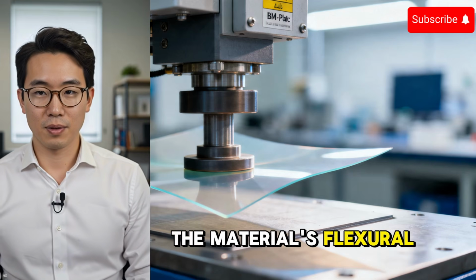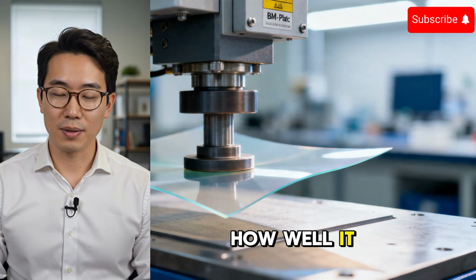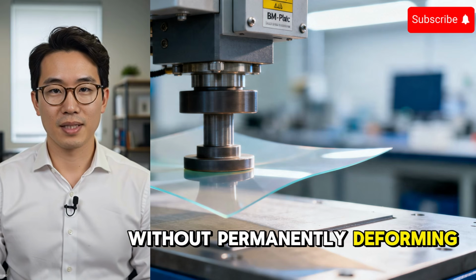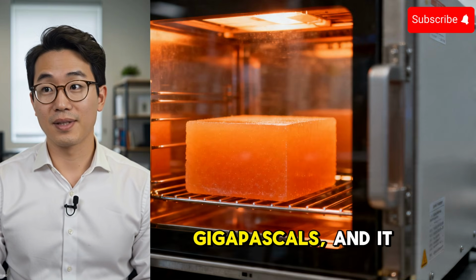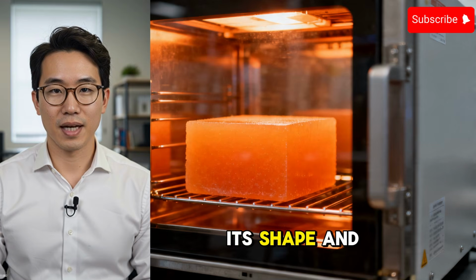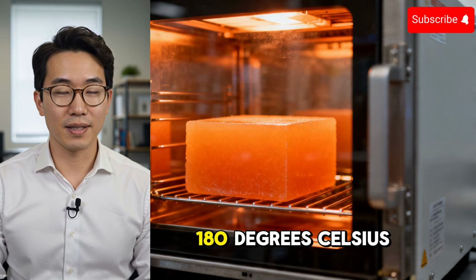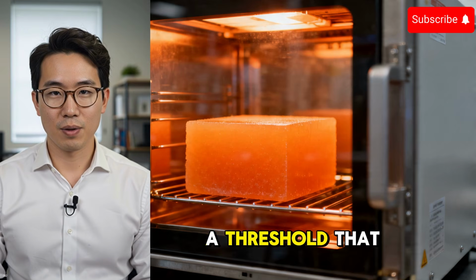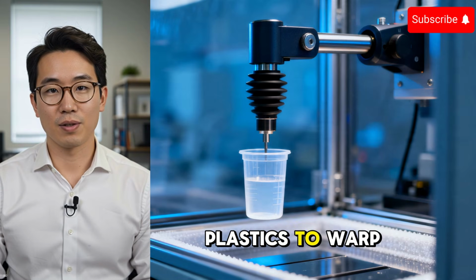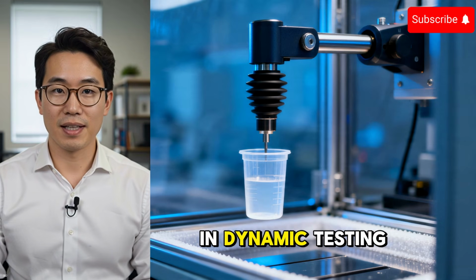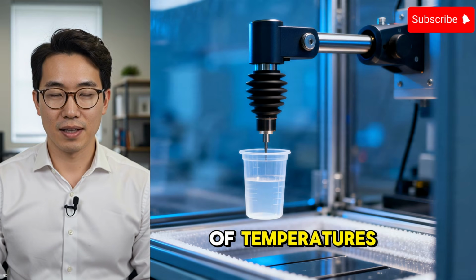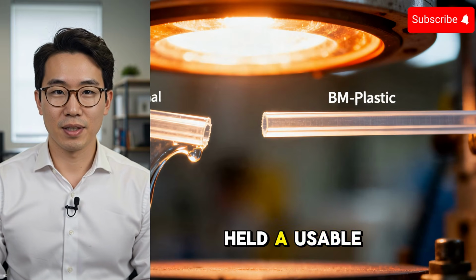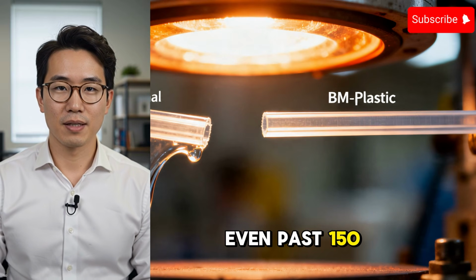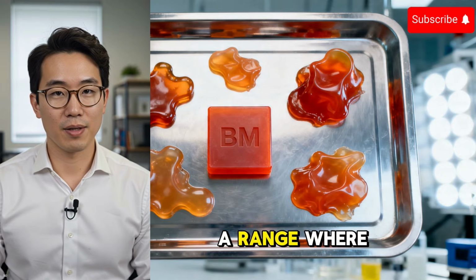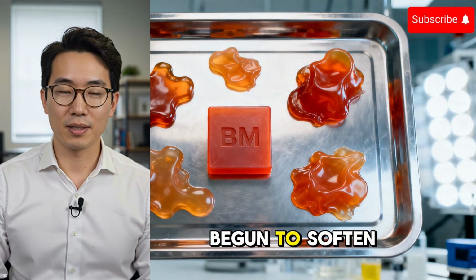The material's flexural modulus, a measure of how well it resists bending without permanently deforming, reached 6.41 gigapascals, and it maintained its shape and toughness at temperatures above 180 degrees Celsius, a threshold that causes many conventional plastics to warp or grow brittle. In dynamic testing that pushed the material through a range of temperatures, BM plastic held a usable structural stiffness even past 150 degrees Celsius, a range where several conventional plastics have already begun to soften and lose their shape entirely.